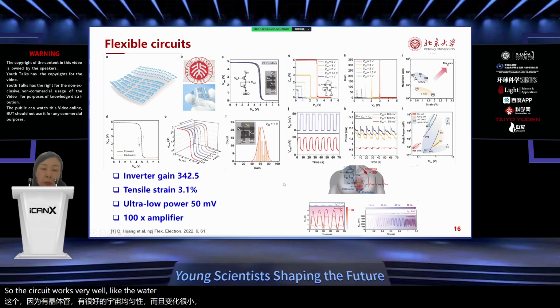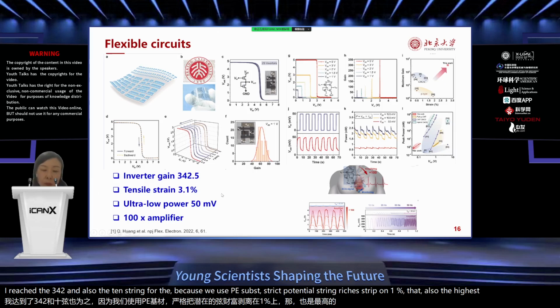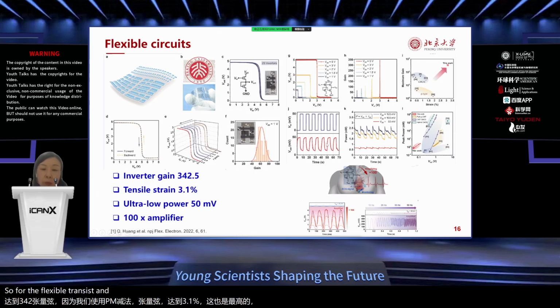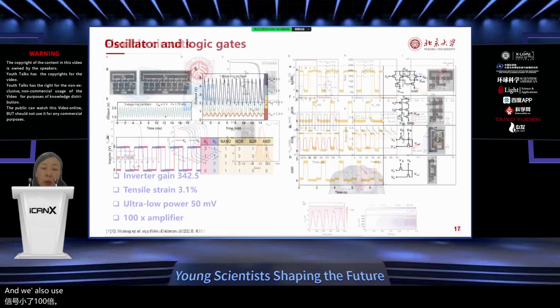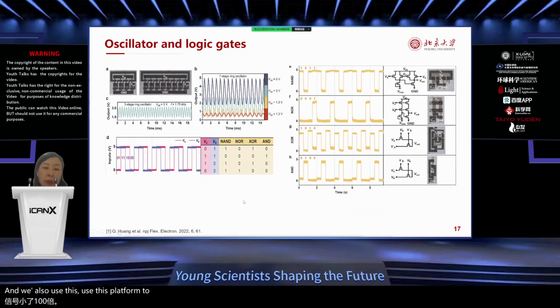The inverter gets the highest gain, a record high gain of 342, and also the tensile strain, because we use a PEN substrate, reaches 3.1%. That's also the highest for flexible transistors. And for the inverter, with just 50 millivolts, it can work very well. Actually, it works in the subthreshold region, and the inverter can also work as an amplifier to amplify a small signal by 100 times. And we also use this platform to fabricate a ring oscillator and different logic gates. It all works very well.